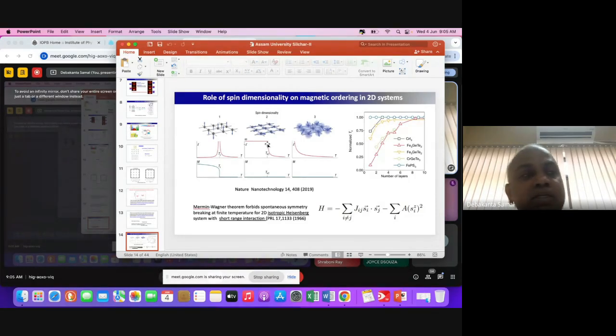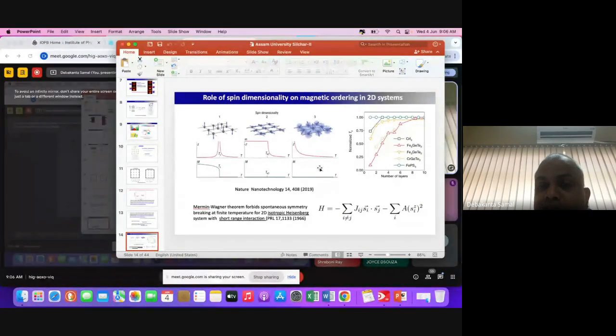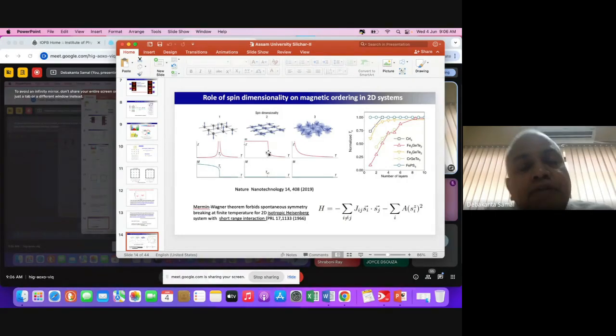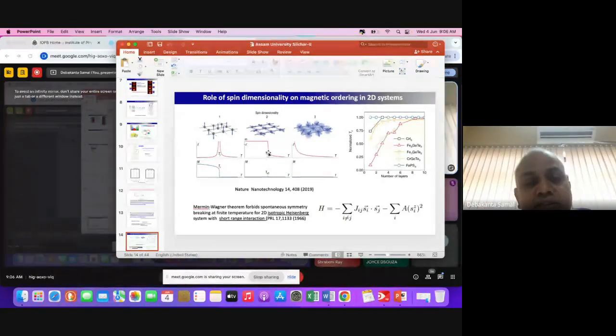And here they show very, very interesting things. You see the magnetization is still zero, like in the Heisenberg case. But if you look at the susceptibility, there is a divergence. And this divergence indicates there is a phase transition. Some sort of phase transition is happening. And this is a kind of topological phase transition where the spins form vortex and anti-vortex. So this is very interesting.